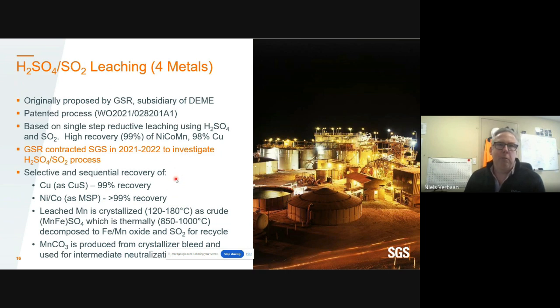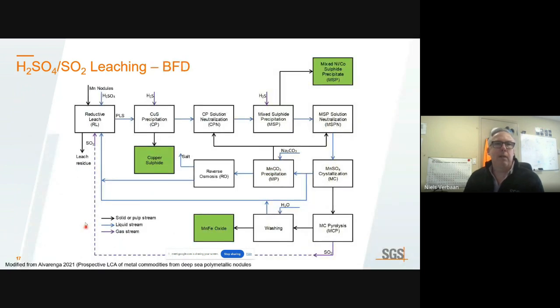We've done a bit of work on the back end of the flow sheet, the liquid treatment part of the flow sheet, showing that we can get high recoveries of copper as a copper sulfide product, and nickel cobalt as an MSP, mixed sulfide precipitate, that's what that means. And there's a few novelties within the flow sheet, and the next slide has the actual flow sheet, but leached manganese is crystallized at elevated temperatures as a crude manganese iron sulfate product, which is then thermally decomposed to an iron manganese oxide and SO2 for recycling.